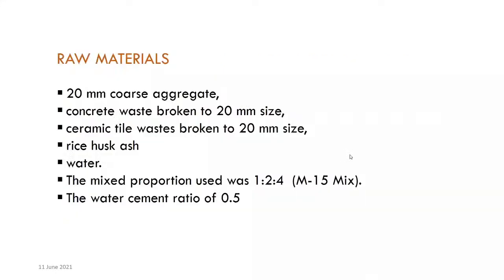The raw materials adopted were the 20 mm coarse aggregate, the concrete waste and the ceramic tile waste, both broken to 20 mm size, the rice husk ash, and water. The mix proportion we adopted in this research was the M15 mix, 1:2:4, and the water cement ratio of 0.5.